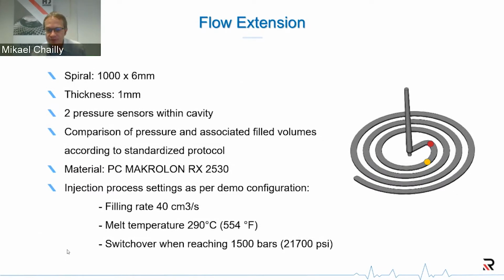So if we go to this second study, which was made for the spiral flow, we have this mold that we have available internally or at partners, where we have this very classic spiral flow. We can use different thicknesses. In the results I'm going to present, we're looking at a thickness of 1 millimeter.